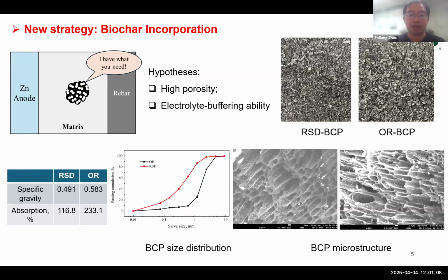So our hypothesis is that the initial performance of sacrificial anodes should be limited and its durability should be enhanced with biochars. In this research, we considered two kinds of biochars, called the RSD and the OR biochars. They are very highly porous, and the SEM pictures can show that. Their water absorption rates are high: one is over 110%, the other is over 233%. Their sizes range from 100 micrometers to even millimeters.